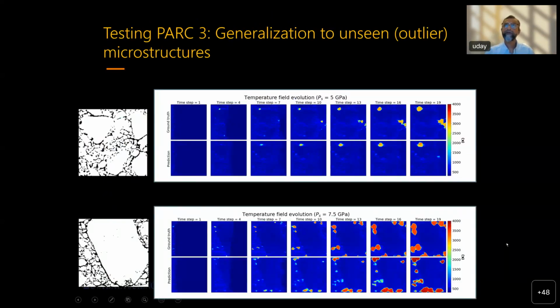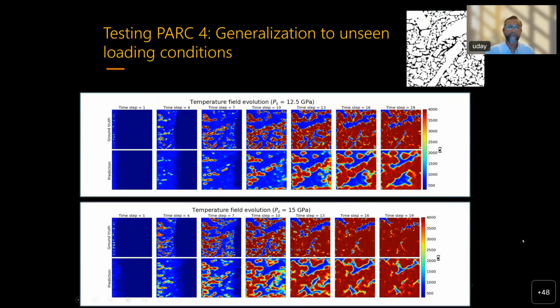Then we also looked at outlier microstructures. We had trained PARC on a certain set of microstructures, and then we picked parts of the microstructure that were quite different from what we had trained PARC on. And we looked at whether it can actually predict the sensitivity of those. For example, for a very large crystal like that, we do a DNS, and then we also look at PARC and ask whether PARC can predict where the hotspots are. We also tested PARC on unseen loading conditions. That is, we trained PARC on a certain set of pressures and we looked at other pressures. And there as well, PARC captures the physics and gives us the correct hotspot growth rates.